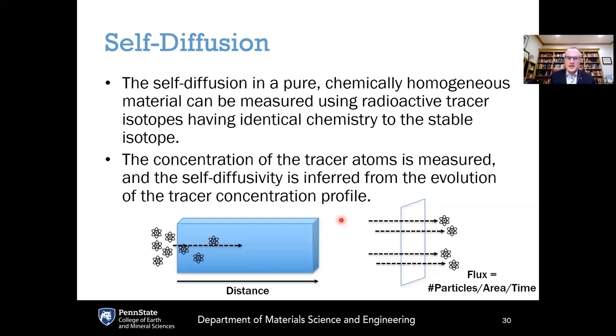The last topic for today, or actually two more topics, one of them is self-diffusion. This is if you want to study the diffusion rate of an atom in a chemically homogeneous material. The problem is that you can't distinguish the diffusing atoms from the ones that are already there. The solution is to use radioactive tracer isotopes that have identical chemistry to the stable isotopes, but because they're radioactive, you can measure the amount of radioactivity and relate that to the concentration profiles of the isotopic species.